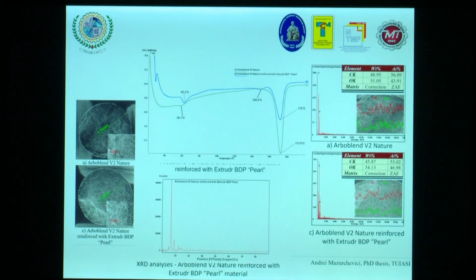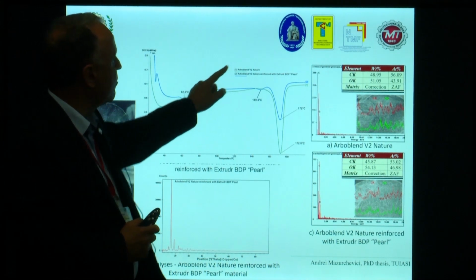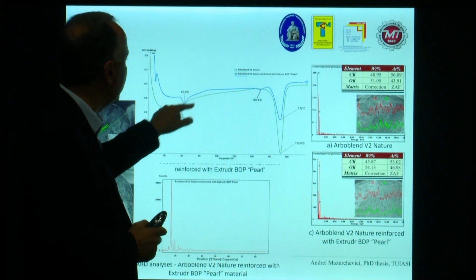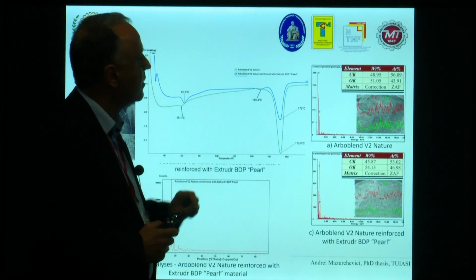Okay. So you can see also XRD analysis in case of Arboblend V2 Nature reinforced with Extrudr BDP. As I mentioned before, you can see the shape of the diameter, quite good, and the diameter 1.74 millimeters. You can see also the diameter for Arboblend reinforced with Extrudr BDP. DSC analysis also for Arboblend: Arboblend reinforced has the same shape and glass transition temperature. And of course, you can see also the main elements.